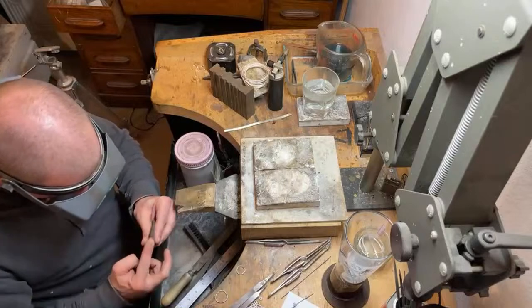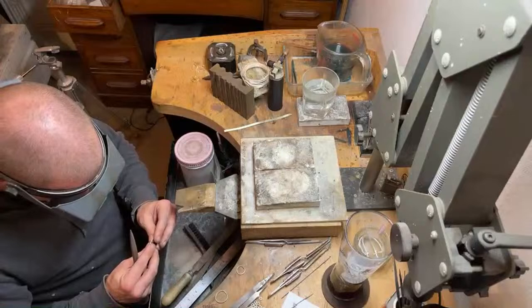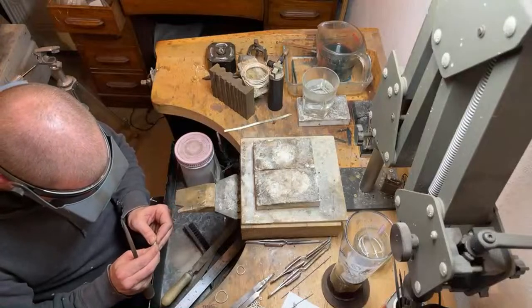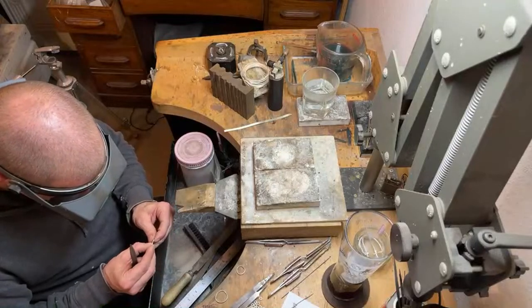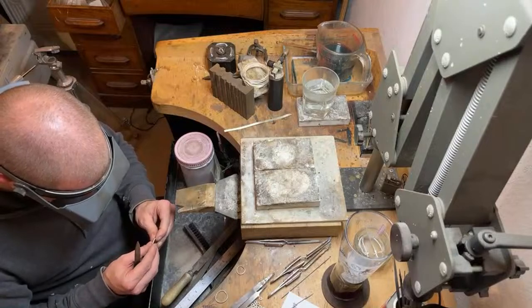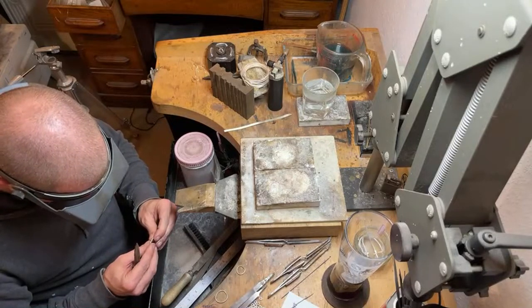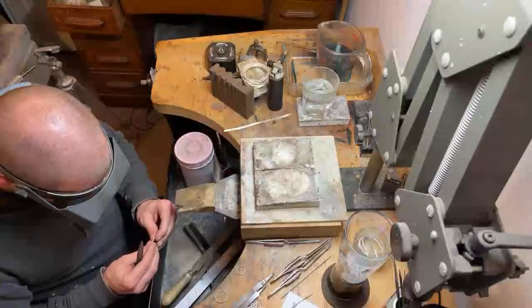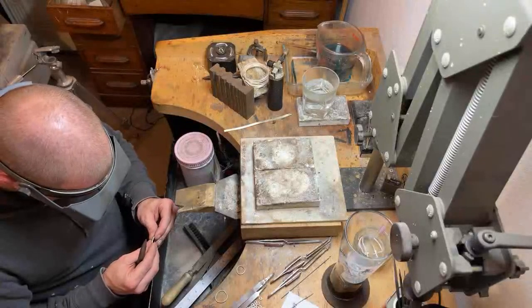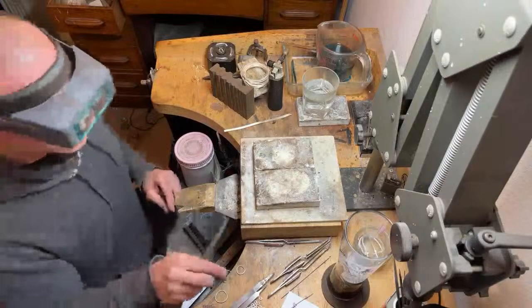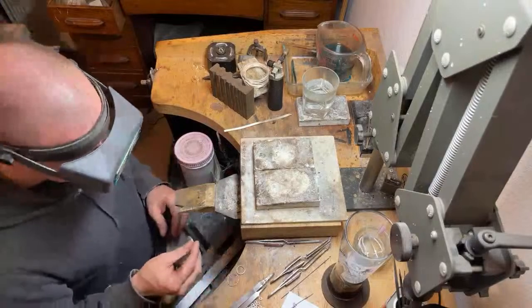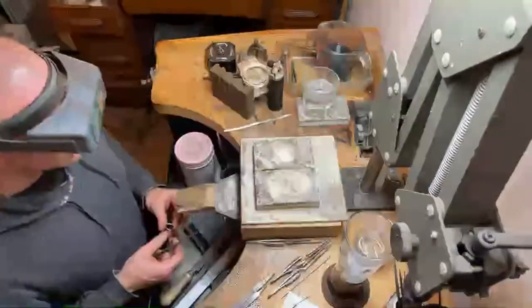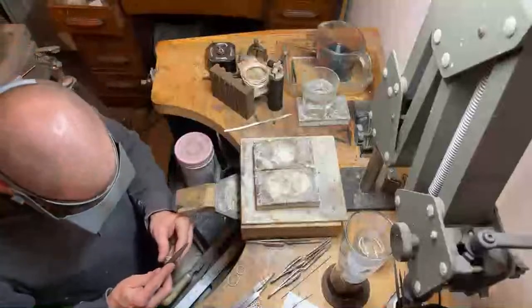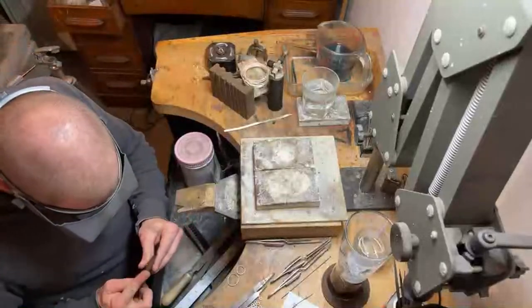The thing with this handmade wire, I haven't tested this batch out, but it's almost like it's anodised. There's an oxide layer, and it can only be silver oxide. When you try and solder it without filing the surface off, you have to file it. I've tried barreling it with abrasive barreling compounds. I've tried electrolytic polishing it.